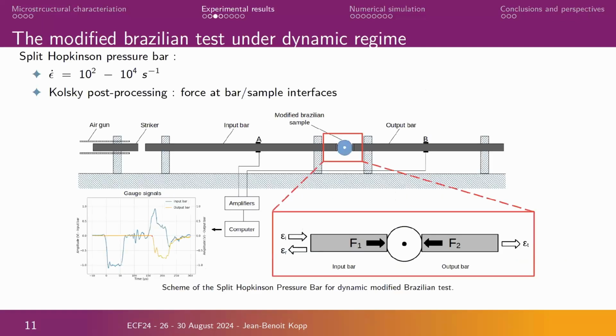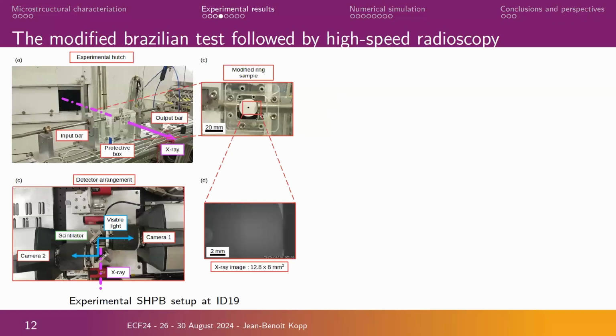So as I said before, this kind of geometry is easy to apply to a split Hopkinson bar in dynamic. So this is what we made. It's very classical, and we use a specific Kolsky post-processing to estimate the forces and the stress applied to the sample. The particular thing we have made in this study is to do this experiment on the ID19 beamline at the ESRF. So it was possible to follow the fragmentation of the specimen with a specific radioscopy. So we have the X-ray signal, and we use 2 high-speed cameras to follow the fragmentation and the cracks at approximately 4 million frames per second.